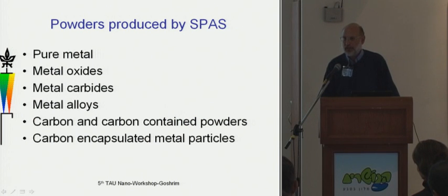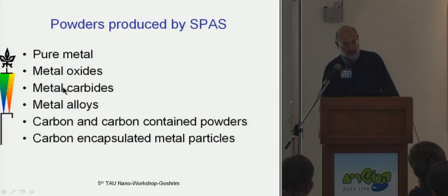After you let this process run and then evaporate the liquid, you're left with a powder that can be pure metals, metal oxides, metal carbides, various metal alloys, various kinds of carbon and carbon-containing powders, and carbon-encapsulated metal particles. And what I'm going to do for most of the rest of the talk, until Yael starts waving at me and telling me that I should conclude, is go through basically a zoo of various kinds of particles that we've produced in the lab.